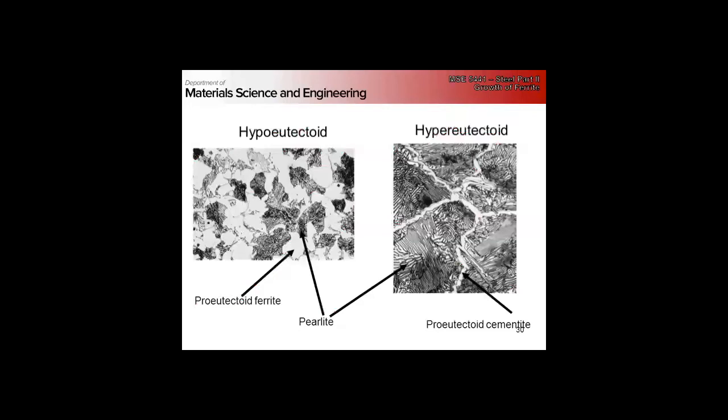And the cementite interface tends to be higher. The cementite will spheroidize at longer times at temperature. You can give the spheroidization heat treatment, but it involves quite a bit more complexity in terms of diffusional mechanisms, rather than just partitioning carbon out for growing pro-eutectoid ferrite. It's not a complete answer, but it's right.